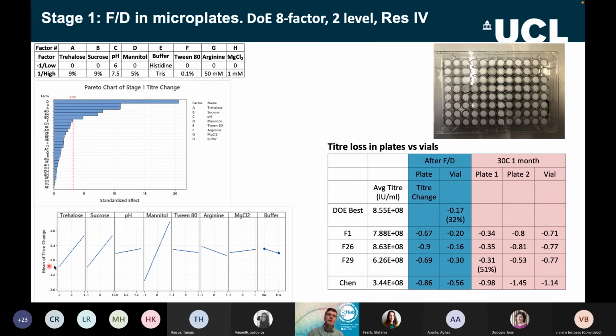And then if we look at individual factors, you could see which way they go in terms of the impact on titer. Going from -1, where you don't have any mannitol, up to 1, where you have the highest concentration, you get an improvement in the titer, and same with sucrose and trehalose. The other factors are much less obvious, not doing much. In fact, we decided magnesium chloride might not be important to put in at all. And a rule of formulation is if it's not doing anything, take it out.